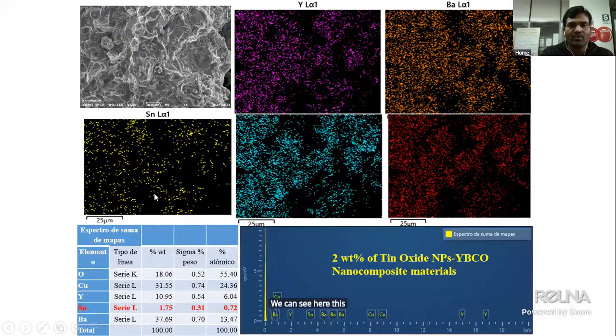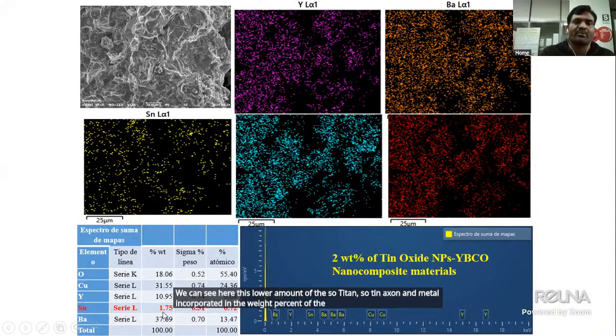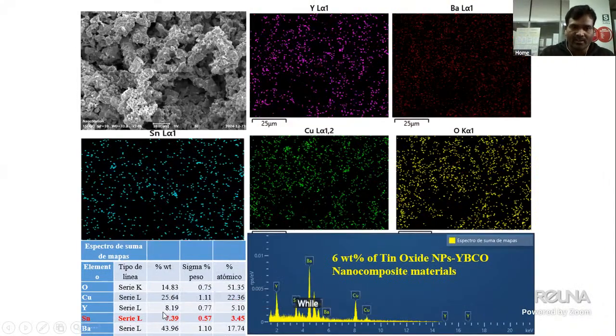So here is the elemental analysis. It is going to identify the EDX analysis. We can see here that at the lower amount of tin oxide metal incorporation, the weight% of the tin oxide is 1.75, while for the higher weight% we can say 7.39. So that means the higher percent confirms the incorporation of the tin oxide metal in the YBCO superconducting material.